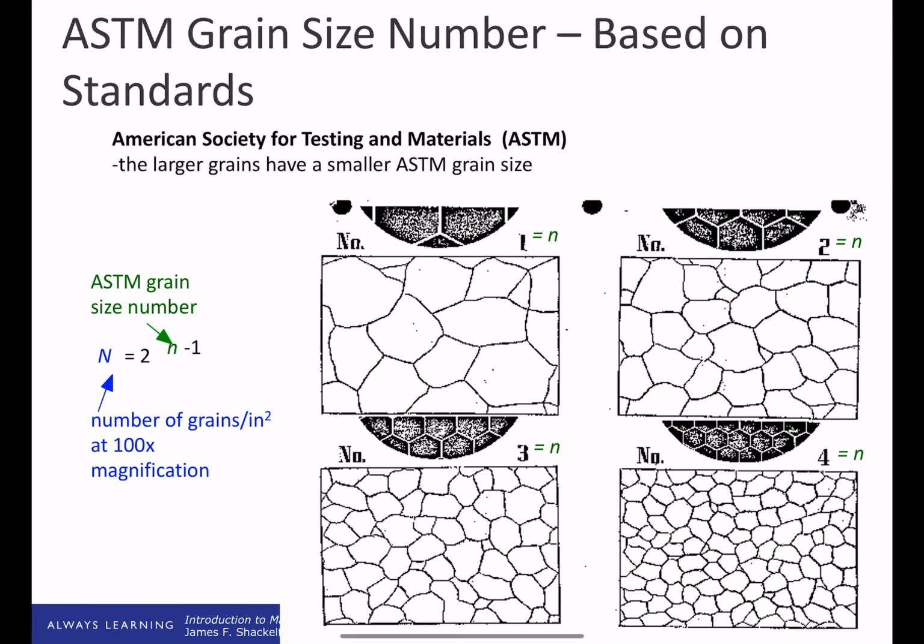Okay, very good. So the basis for this equation, if you want, is putting a bit of a fractal approach or model between the two, between actual images and a sort of honeycomb type lattice to occupy the area of the image. So that's the fundamental basis for this equation, and how we carve up general area to give this. So the ASTM grain size number is evolved from this concept.